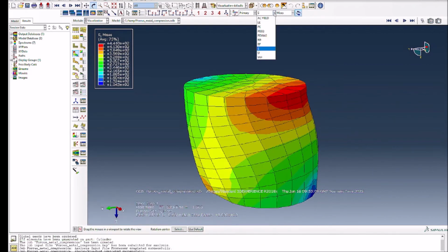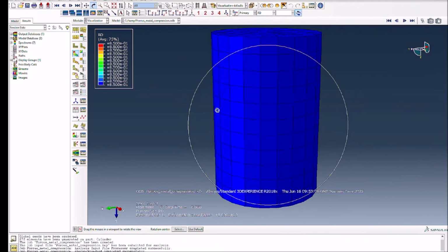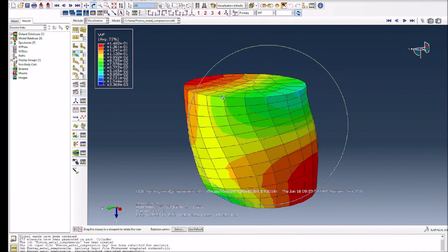Also, in the same model, we can see relative density, that how it evolves. So you see it started from 0.85, which is this initial value. And then as the deformation progressed, the material was becoming more dense because your voids were contracting, basically, and we reach up to 0.996. So now we go back, and also you can look at the void volume fraction as well, plastic strain, etc., due to the deviatoric part. So this is how you do it.